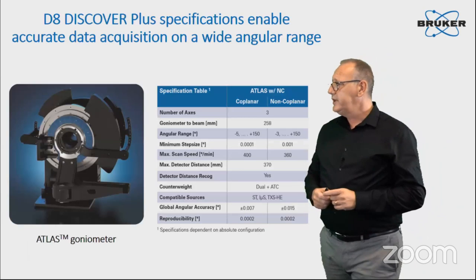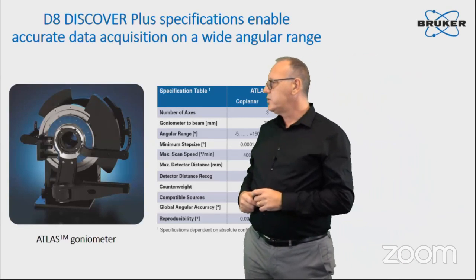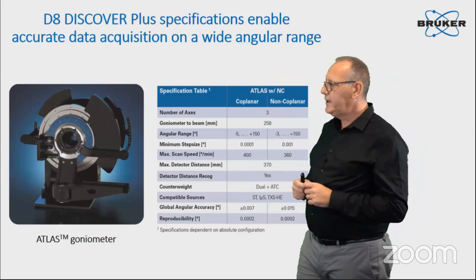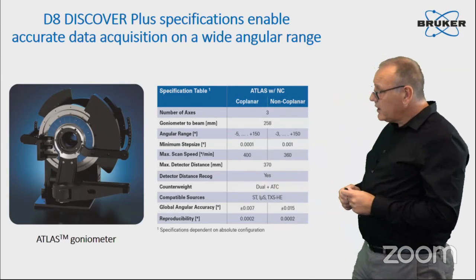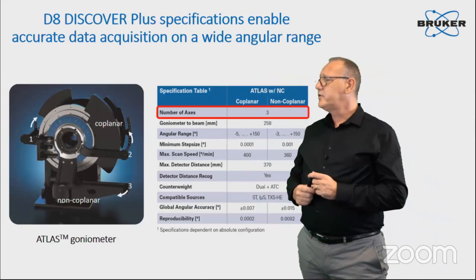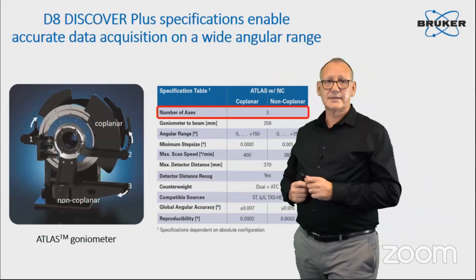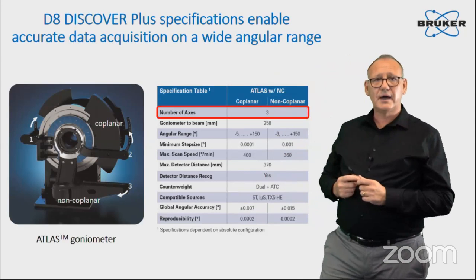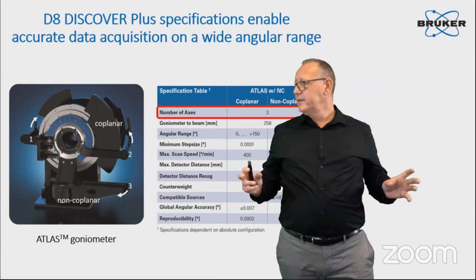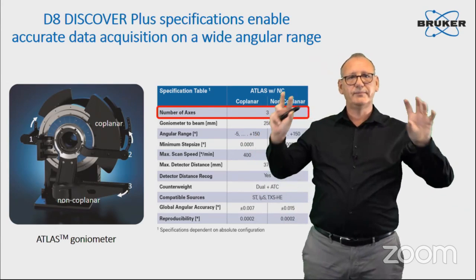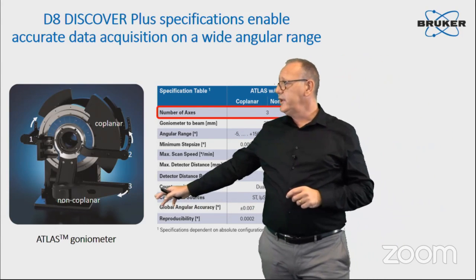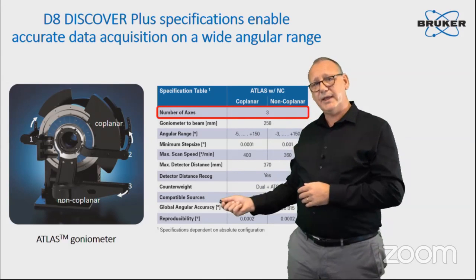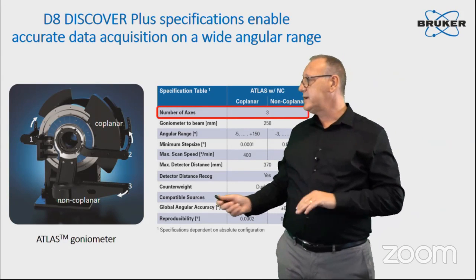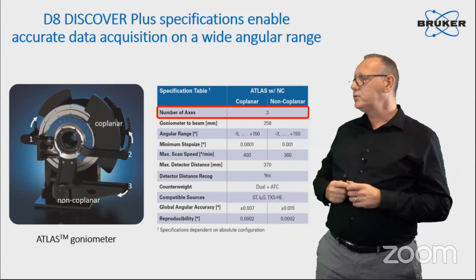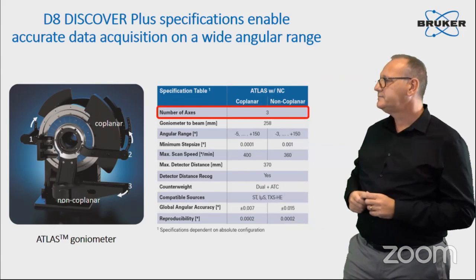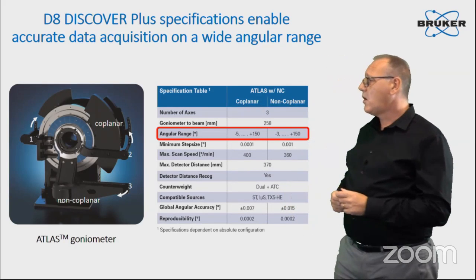I would like to show you here the so-called Atlas goniometer that can fulfill all those diffraction geometries. This goniometer is equipped with 3 scanning axes. The first one is on the tube side. The second one is on the detector side. This is the classical coplanar diffraction geometry. But there is a third axis, number 3 here, that allows you also to scan in plane while keeping your incident beam grazing on the sample. This will allow you to analyze in-plane properties.